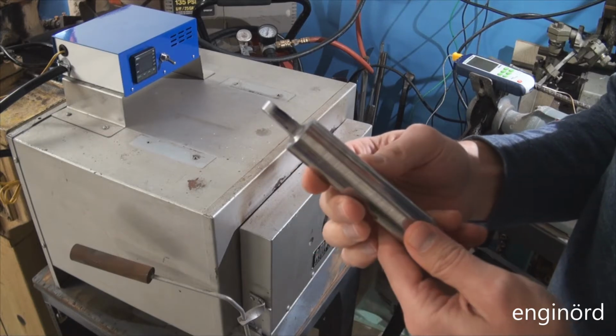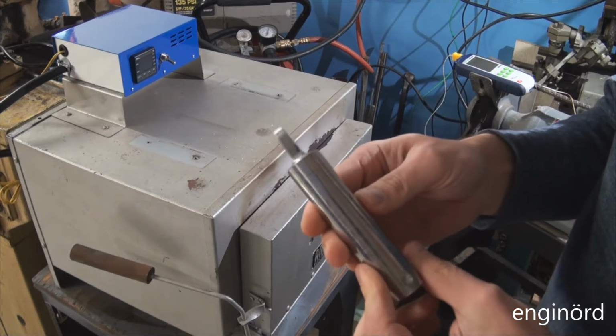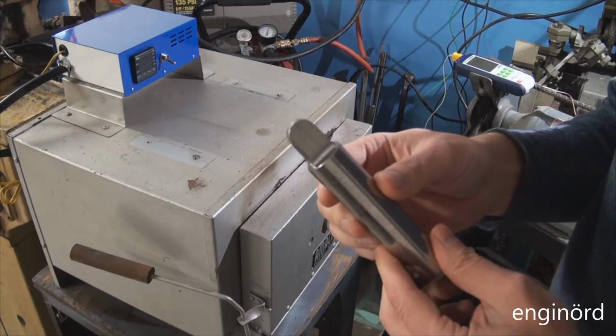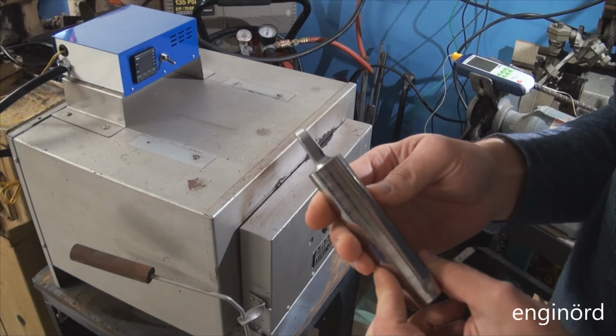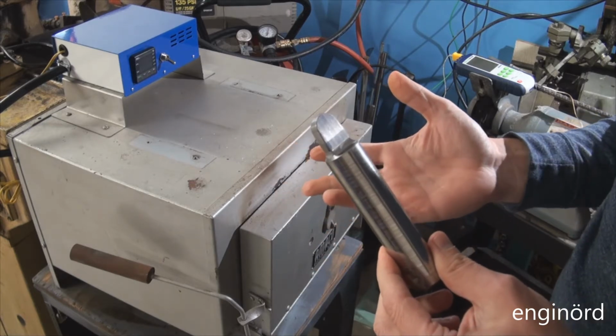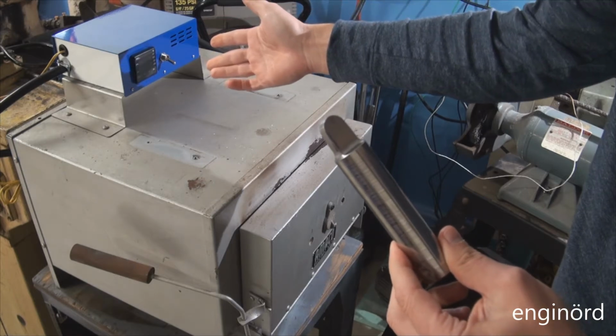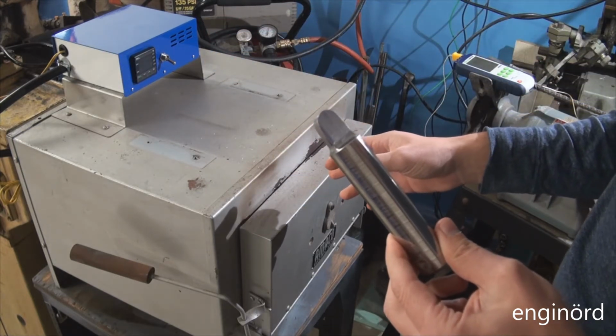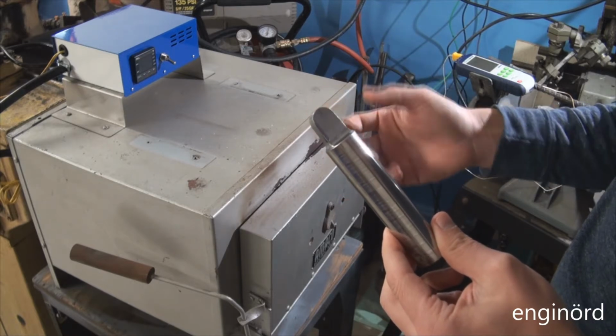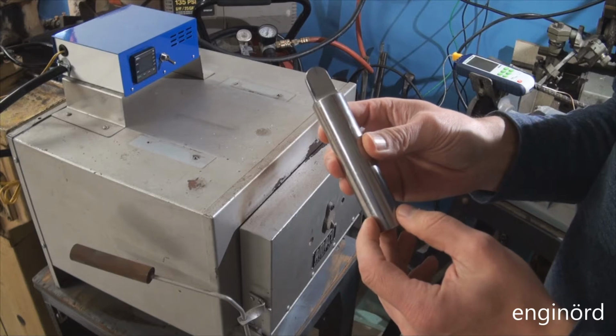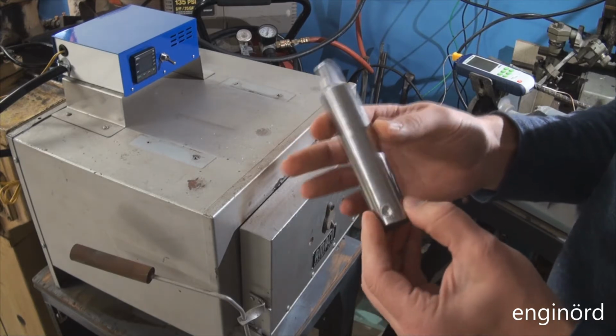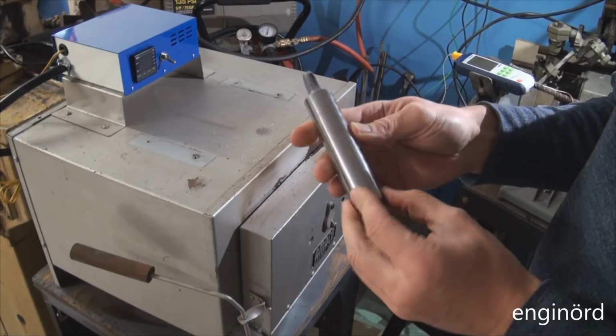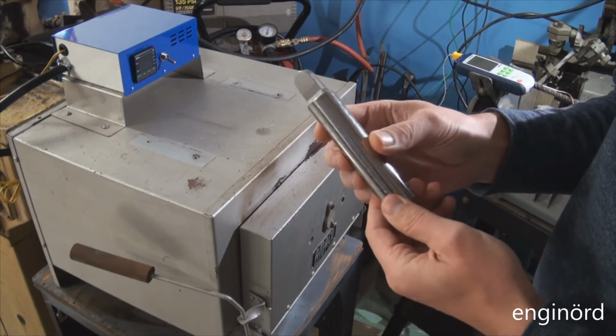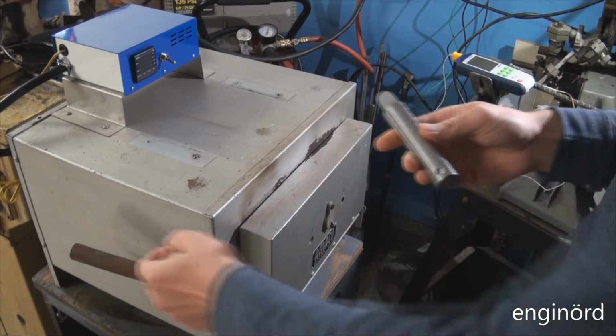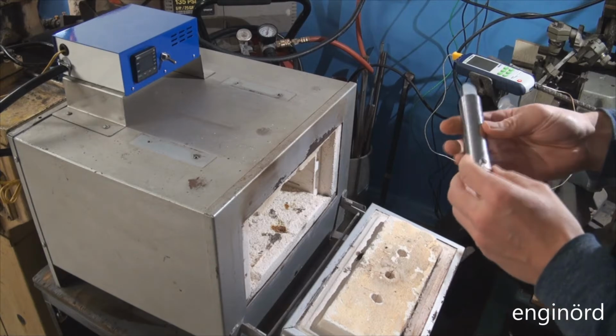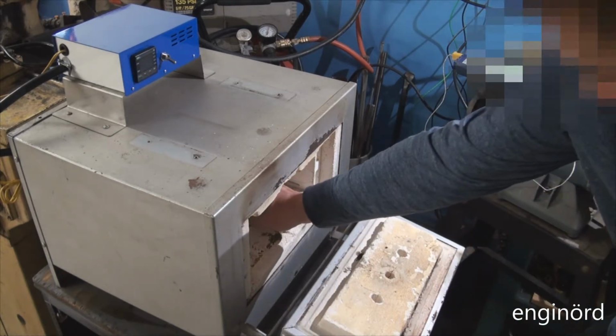it's O1 tool steel, so I'll have to bring up the temperature to 804 degrees, and there's a recommended rate which my controller will not be able to do, so it will reach the 804 Celsius in about 3 hours, and then I'm gonna have it soak for another half an hour. This is 1 inch diameter, so that should be adequate. So, ladies and gentlemen, please place your O1 tool steel pieces, because the doors are closing.